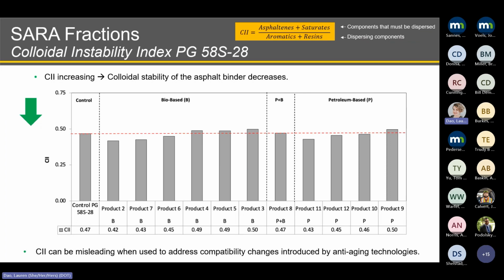Regarding the chemical evaluation of the treatments, as mentioned before, we did the separation of the 4 asphalt fractions. With those asphalt fractions, we calculated the colloidal instability index. Basically, we wanted to see the components that must be dispersed divided by the dispersing components of the binder. And we wanted this colloidal instability index to decrease, which means that our asphalt binder is more stable. You can see here that in comparison to the control, the majority of the products, regardless of whether they are bio-based, petroleum-based, or hybrid, seem to decrease the colloidal instability index of the binder after 1 month of treatment application.